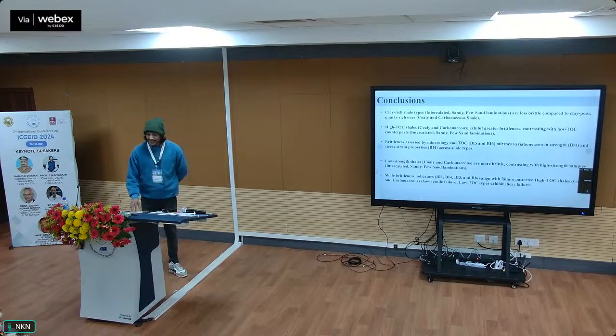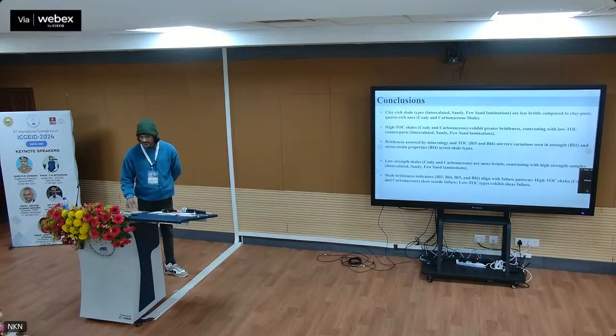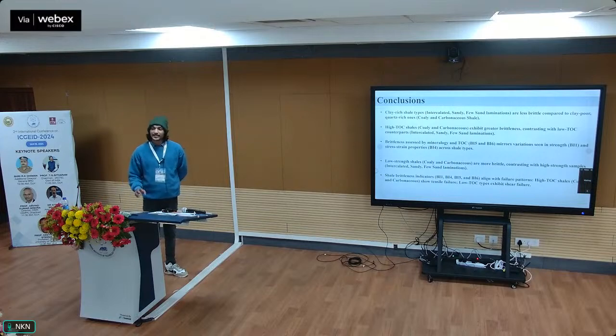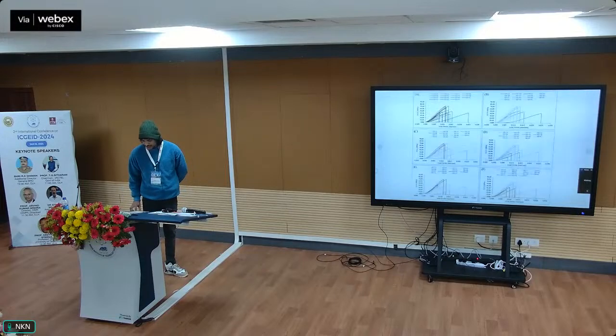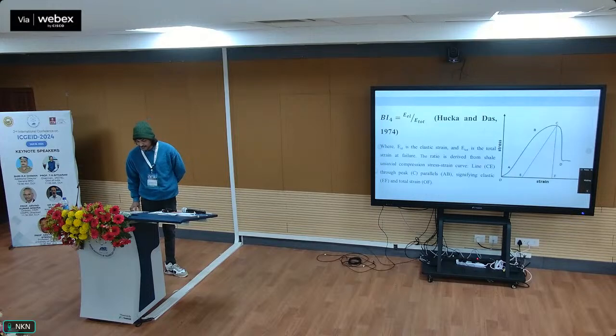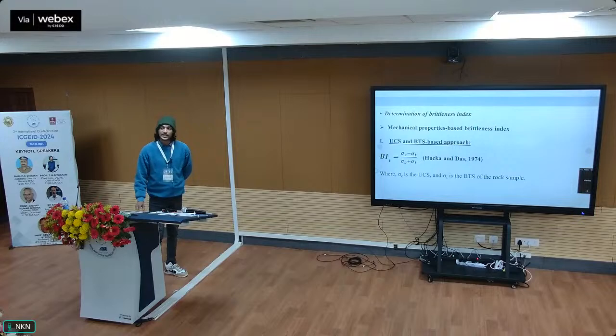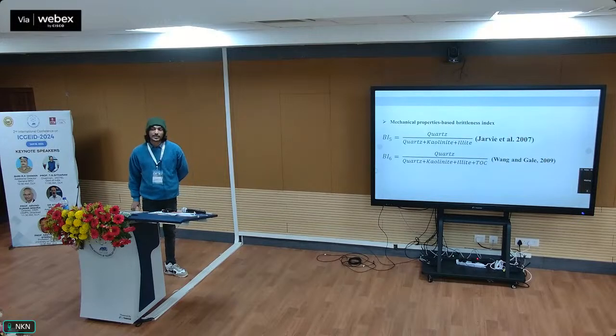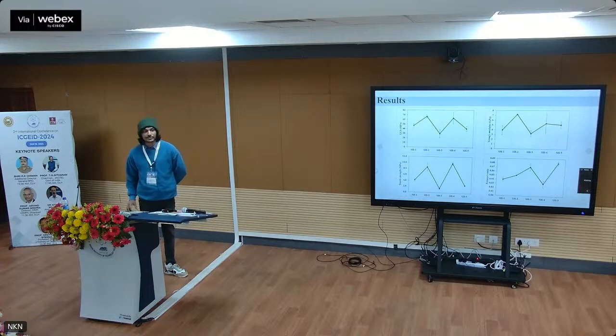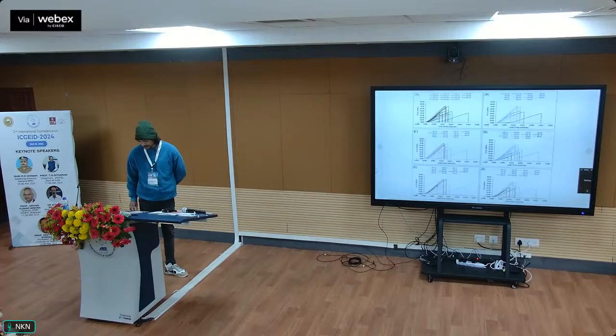So in conclusion, clay rich shale types are less brittle compared to clay poor and quartz rich ones. High TOC shales exhibited greater brittleness, contrasting with low TOC counterparts. Yes, so I told you that TOC, the total organic carbon content of a shale, makes it more ductile in nature. But in our result, we got that high TOC shales are actually more brittle compared to the low TOC shales. This happened because in these two samples, the quartz content is very high. It is around 80%, 88%. So quartz has much more influence than the TOC. That's why even with the higher TOC, the brittleness index of these two samples are higher.